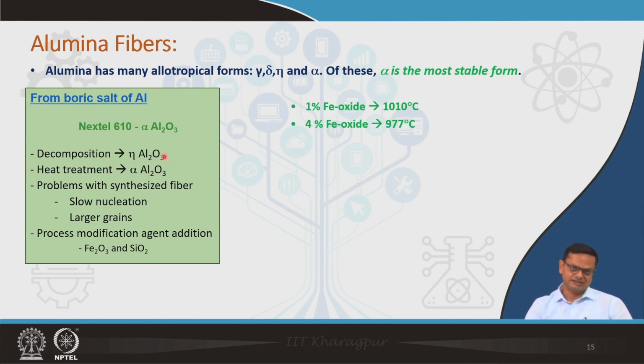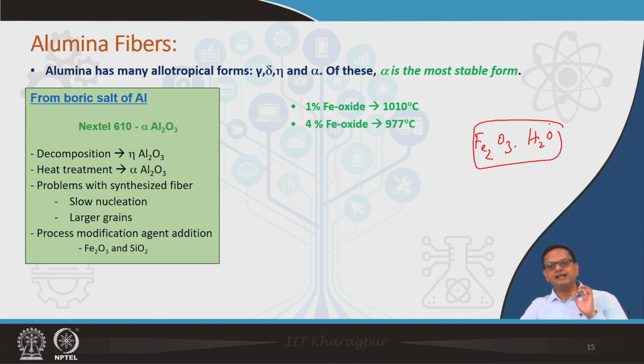And in this process from eta Al2O3 to alpha Al2O3 with heat treatment, the basic problem is that the eta to alpha transformation is a very slow process, and that leads to increase in grain size, and in turn leads to deterioration in the mechanical properties. Okay. So, how do you get rid of this? The idea here is that this slow nucleation process has to be changed to a faster nucleation process, and what can be done for that? A process modification agent or a nucleating agent could be used. For example, iron oxide. Okay. So, Fe2O3, a hydrous Fe2O3 nucleating agent, could be used, and that will enhance the nucleation process.